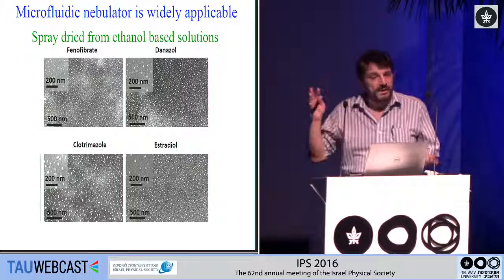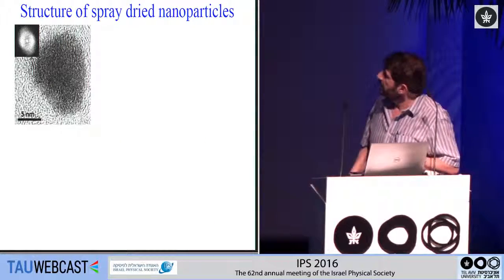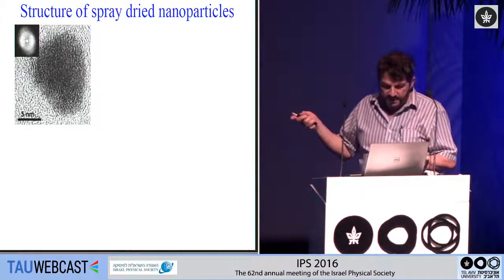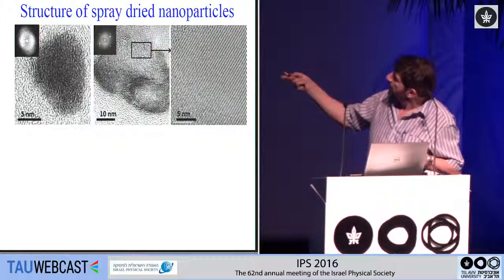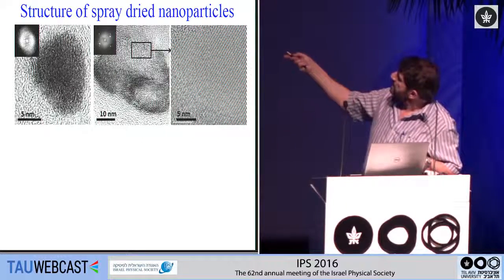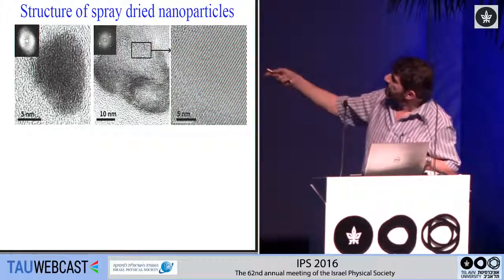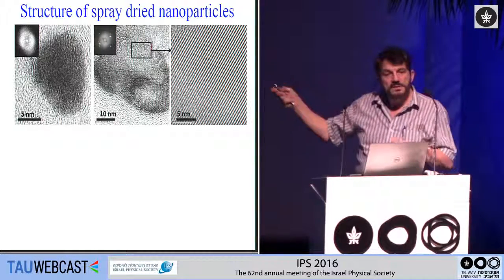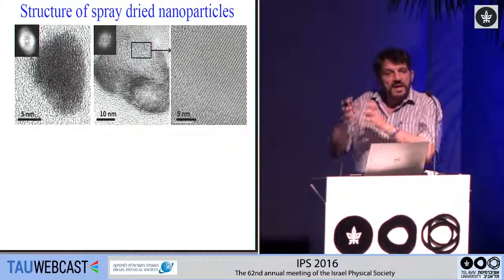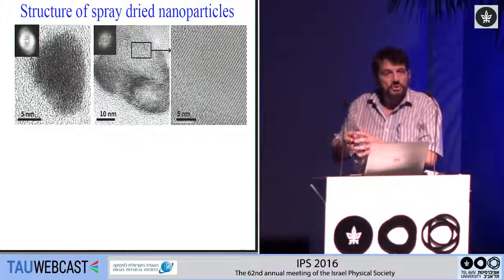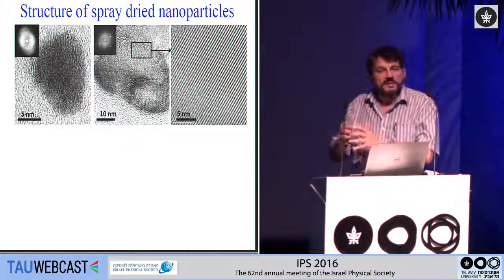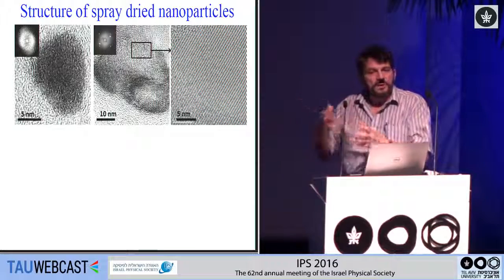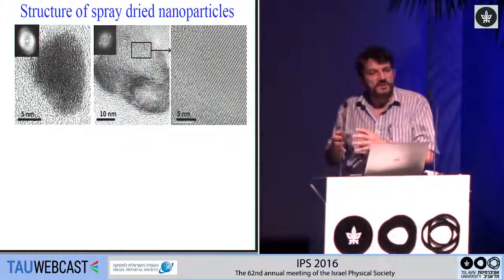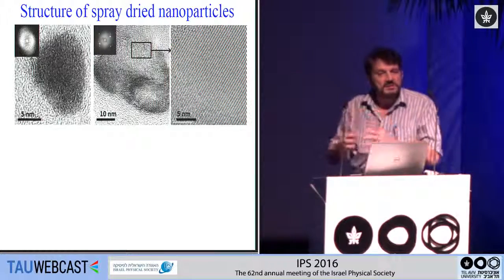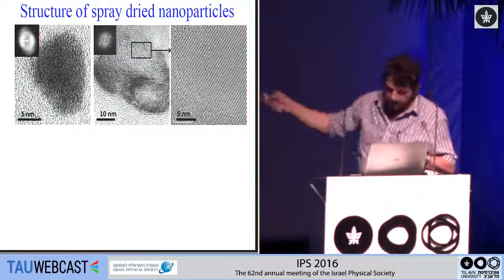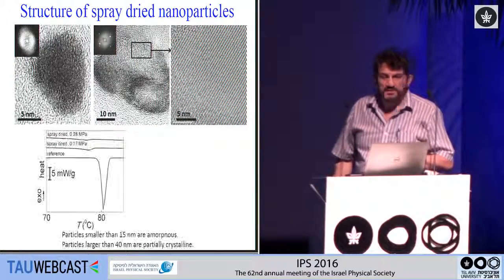But here's the really interesting thing. If you look at the nanoparticles, you see that, in fact, in the larger particles, you can see crystal lattice. The smaller particles, you no longer see any remnants of crystals. All the materials that I showed you are materials that form crystals. They're all organic or inorganic materials that want to crystallize. But if you go to small enough particles, you completely lose any semblance of crystallinity.